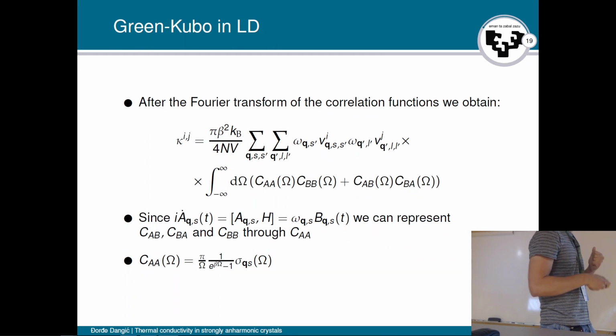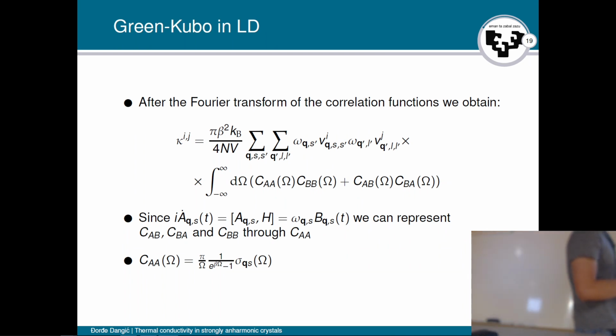Okay, and then we get this expression for the lattice thermal conductivity. And as you can see here, we are keeping the sum over 2 phonon wave vectors and 4 phonon branches. And we have here the already mentioned decoupling form of the two phonon correlation function.